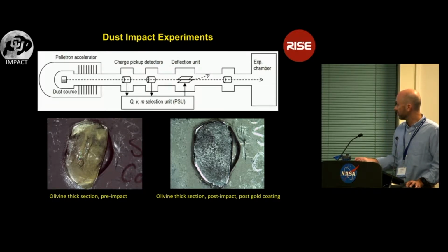These are our target samples. So here's an olivine, San Carlos olivine thick section before irradiation and impact. Here is the olivine section post-impact. It has this kind of big color change, not necessarily because of the impact processes, because we did some gold coating for SEM afterwards, but you can kind of see the surface looks pretty messed up as a result of